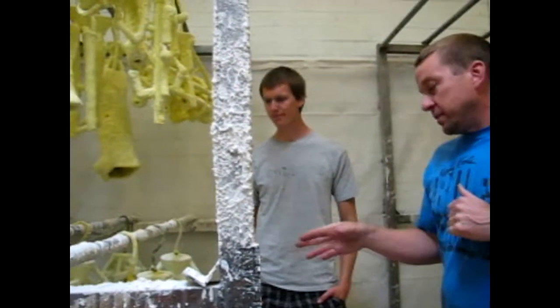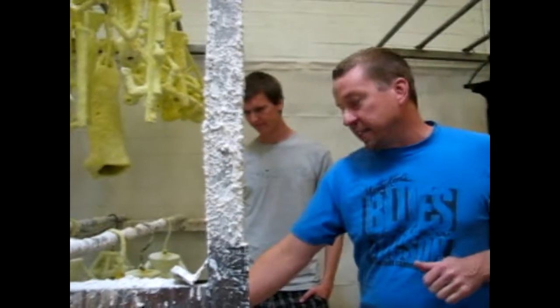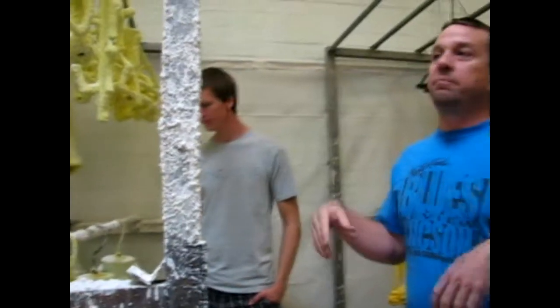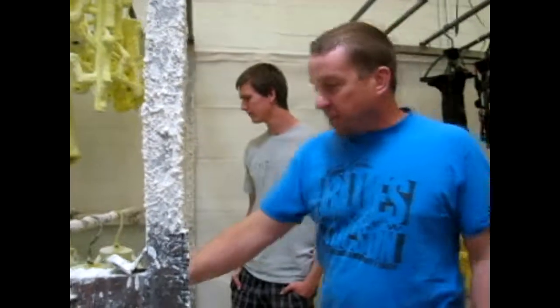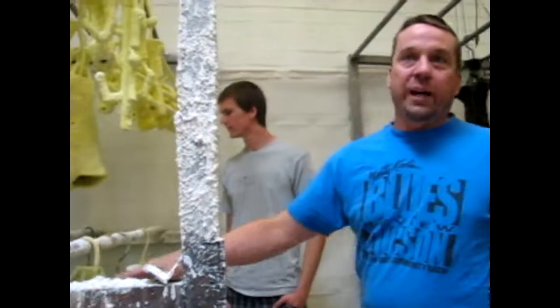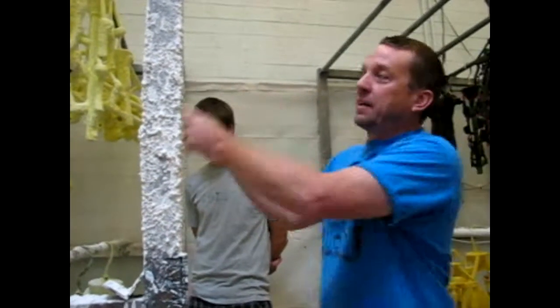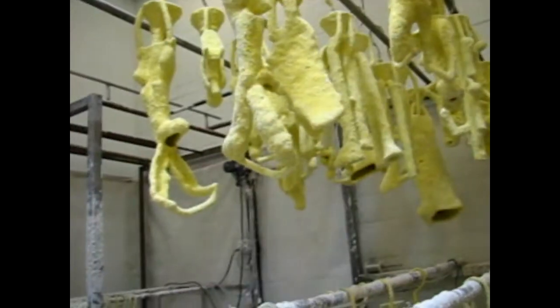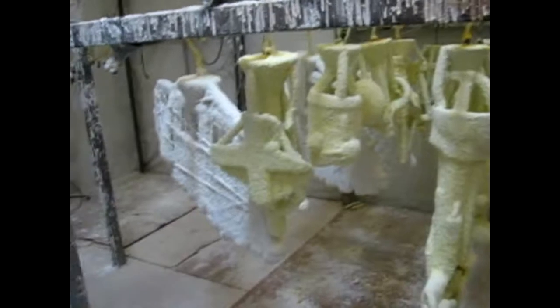There's other foundries that will take these and put them in an autoclave, because it's friendlier to the wax. It doesn't burn it because it's just steam. But you still have to take it after that and fire it. So it's 2 steps, and having an autoclave and steam is expensive and not for us. So we do what's called flash firing, where we do both at once. The wax gets burned up a little bit, we lose some, and it gets brittle over time, but we just replace it. We don't have to fool with autoclave.